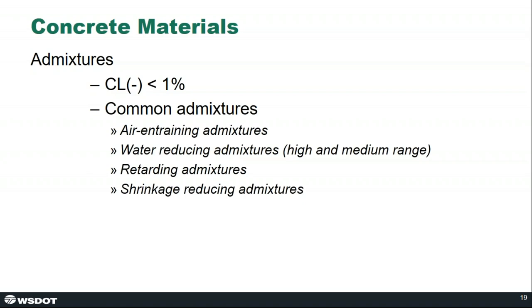Here's a list of some of the common admixtures we see in our bridge deck concretes. The air entraining admixture is key for freeze-thaw resistance. Water reducers and retarders are key for transporting and working mixes. And we also see shrinkage-reducing admixtures in all of our bridge decks. And I'll talk about that admixture a little more in a few slides.